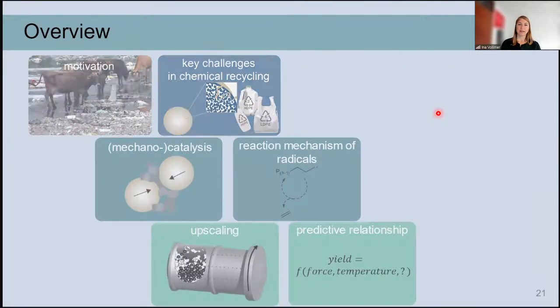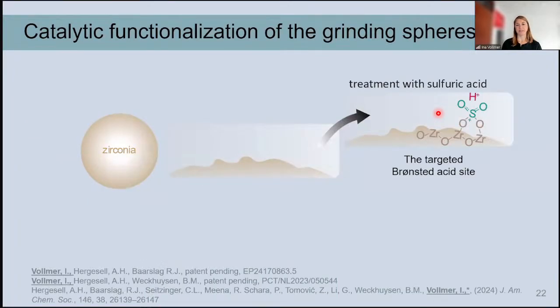And so the idea was then to use mechanocatalysis, and actually direct mechanocatalysis. So instead of adding powder to the ball mill, we directly functionalize the surface of the grinding spheres. For example, we use a treatment with sulfuric acid. And the initial idea was to create Brønsted acid sites because we knew that those were active for thermal catalysis.